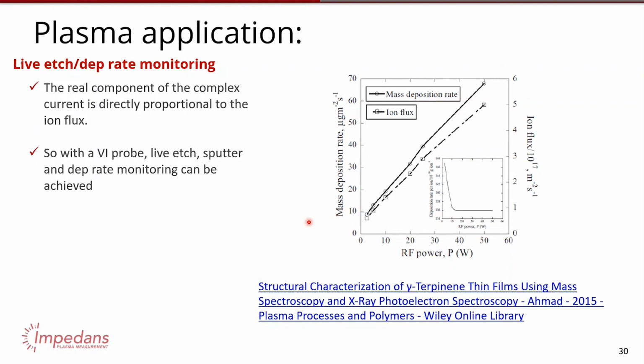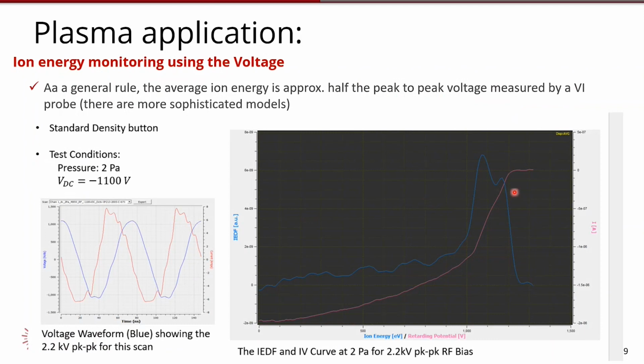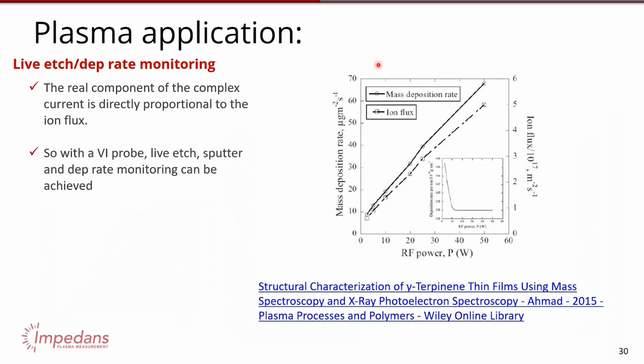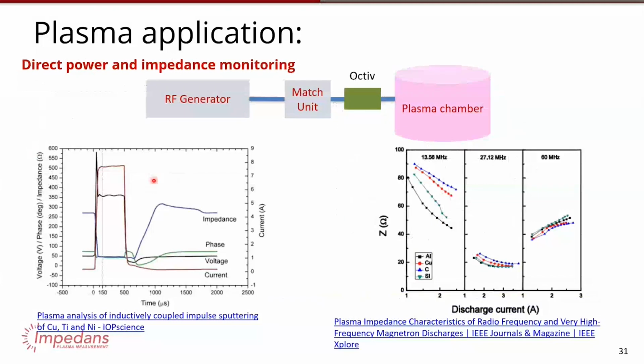So imagine with one of these in place, you can make sure that your ion energies are correct, because in some processes, like say dielectric etch, if they're not high enough, they're not etching. In other processes, if the energies are too high, you're damaging the surface, like maybe in a polymer deposition or something like that. Okay, so this is quite a powerful application. Let's move on. I mentioned earlier, direct power and impedance monitoring is achievable.